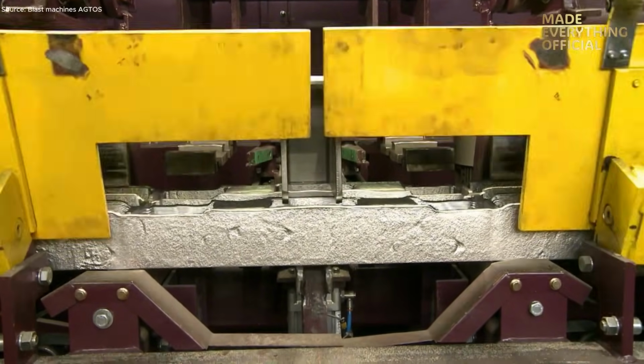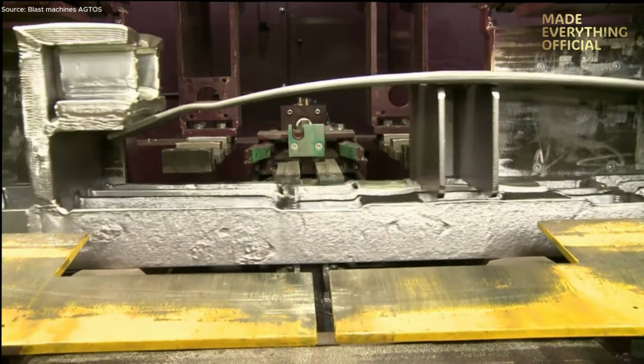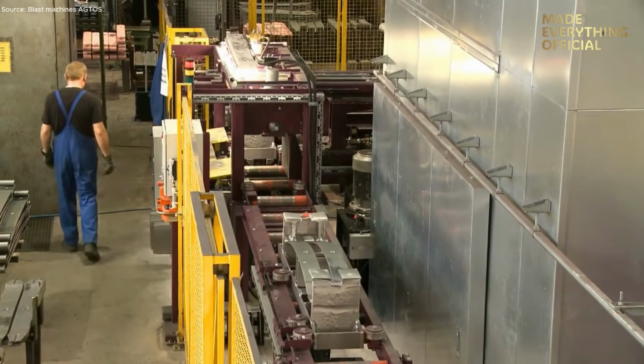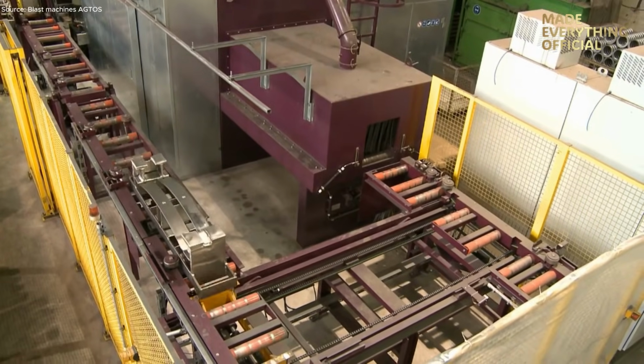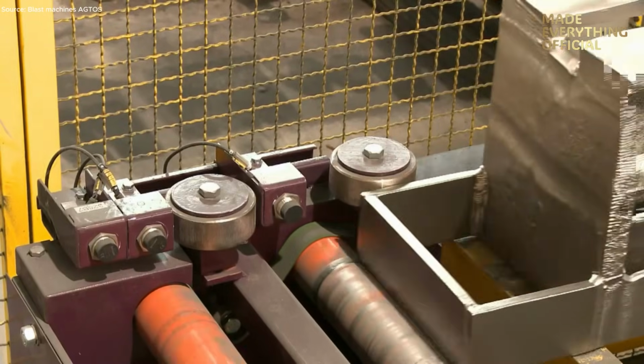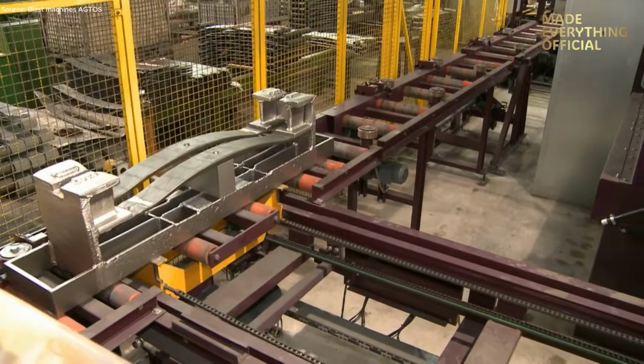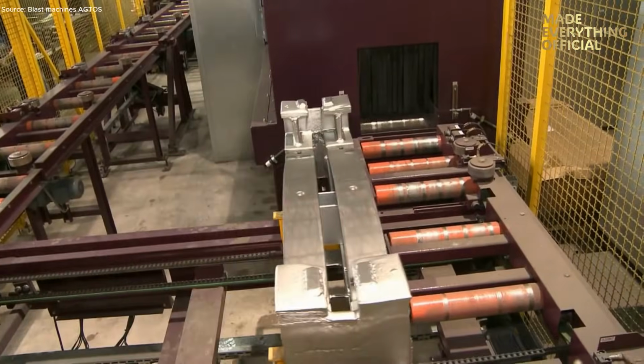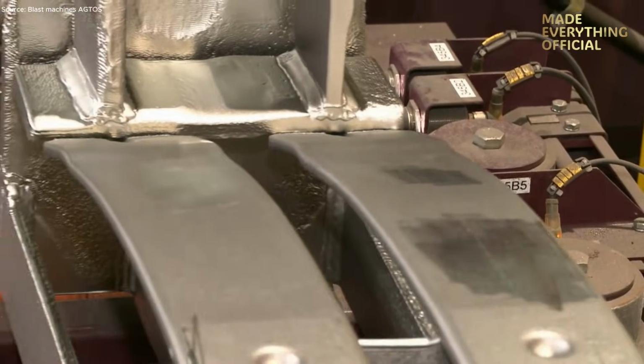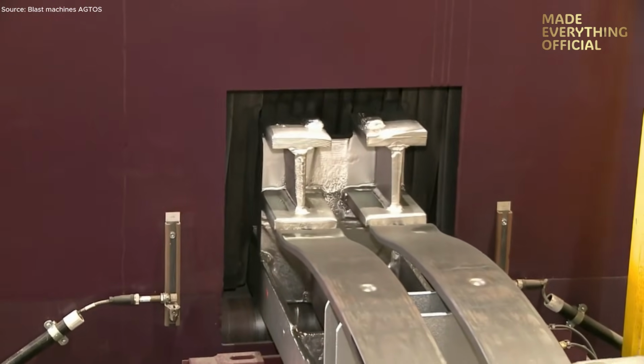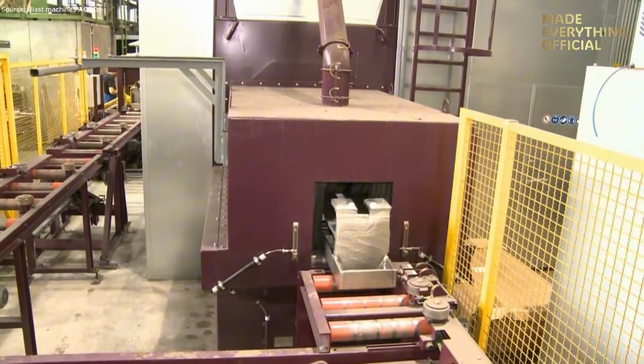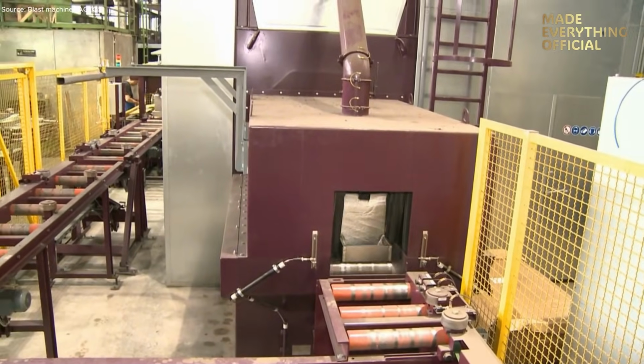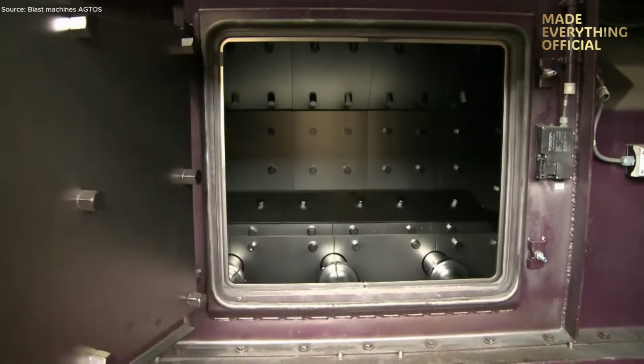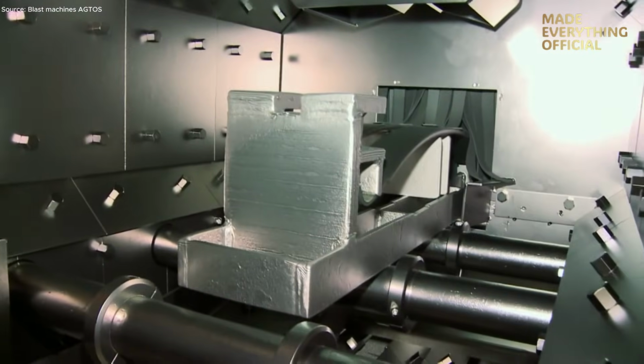Before peening begins, the springs are pre-cleaned, and their surfaces ground to remove any slag or imperfections. Each carrier holds 2 springs at a time, manually exchanged by the operator. Once the protective cover rises, the spring is placed under tension beneath a robust hold-down device. A massive 20-ton press force applies the required pre-tension with a vertical stroke of 200 millimeters, preparing the steel for uniform hardening. Sensors along the conveyor automatically trigger each step as the springs move through the system.